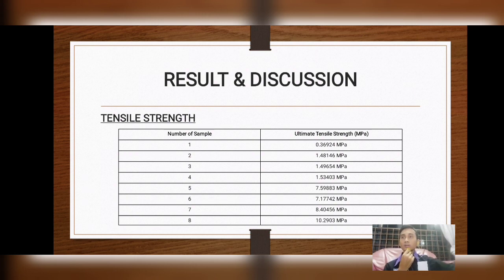Okay, the first result is about the effect of different material parameters on tensile strength. This tensile test uses specimen samples with different parameters applied to them. The highest ultimate tensile strength is sample number 8, which is 10 MPa, while the lowest ultimate tensile strength is sample number 1, that is 0.3 MPa.